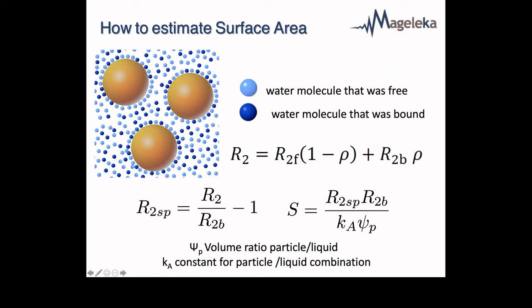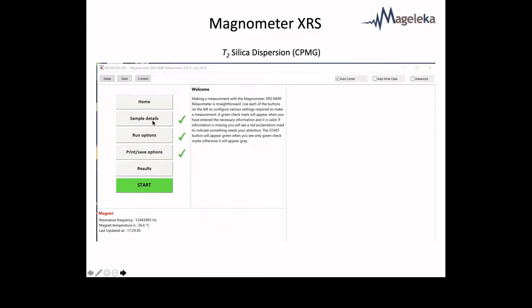So the actual specific surface area, if you've calibrated with Ka, depends on the volume fraction, volume ratio of particles to solvent, and then the relaxation times that you measure, R2SP, and the relaxation time of bulk water. So you can see it's a very, very simple formula. Once you know this calibration, you can get the surface area. Now, if you don't know the calibration constant, you can still produce a parameter which is proportional to the surface area. And in many cases, that's very useful in its own right.